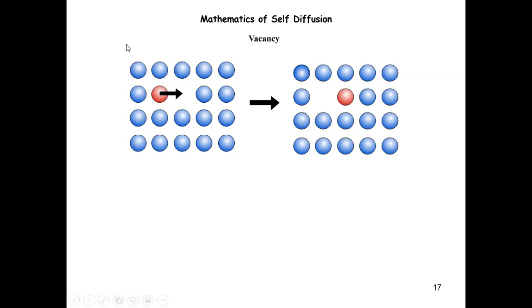Okay, so about the diffusion, in the last class, I think we finished our discussion of the interstitial diffusion. We introduced that by working out a very simple material model, right? And we derived Fick's laws. In Fick's first law, we show that diffusivity, which is one of the most important dynamic parameters related to diffusion, is determined by the physics, in the sense that it's related to the hopping rate, related to the crystal structure of the material, and it relates to the free energy barrier for the hopping, etc.